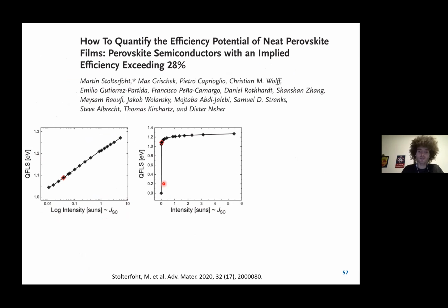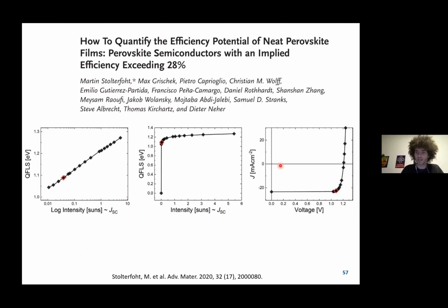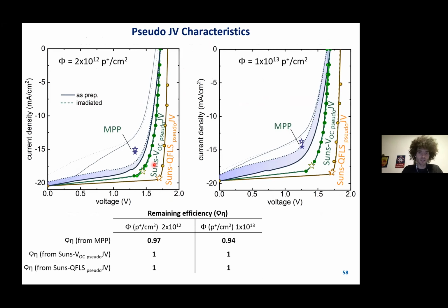And now what you can do is just flip the two axes here and subtract light-induced JSC to get a pseudo-light JV curve. And I'm now doing this for the two tandems and the data I showed you in the slide before. And what you get is basically this. So the green curve here is the pseudo JV from sun's VOC, so from the complete tandem. And then here the orange is pseudo JV from sun's quasi-Fermi level splitting of the bare absorbers. And I do this for the 2e12 protons per square centimeter and 10 to 13.